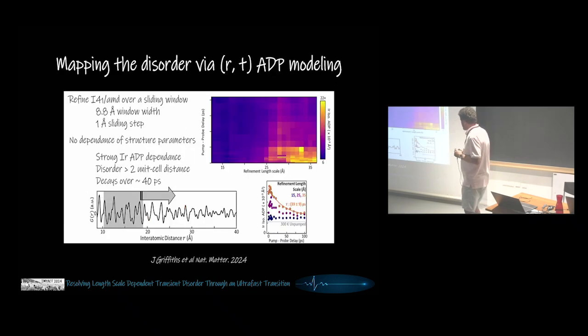So if you focus on one of those models, specifically, I think it was a tetragonal model, it does not really matter, and you do a sliding window refinement. You select the window size, and you refine your data over different ranges, and you extract parameters that you obtain from such fits. It turns out that the only parameter that really changes in some meaningful way is the atomic displacement parameter of iridium. And so this is the map of the iridium displacement parameter as a function of, on the x-axis, refinement range, and on the y-axis, pump probe delay time.